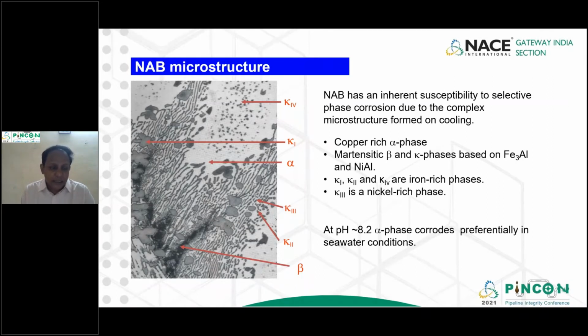It means, like we know that in the case of brass, where you have a copper-zinc alloy, the zinc selectively goes because it's highly electrochemically active compared to copper. Similarly, here with the phases, we have to see that the alpha phase, which is rich in copper, preferentially corrodes in seawater, which has been seen in this condition. So now I'm going to see these behaviors in an erosion-corrosion environment.